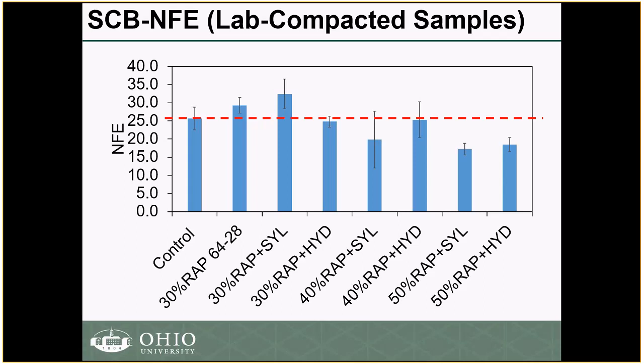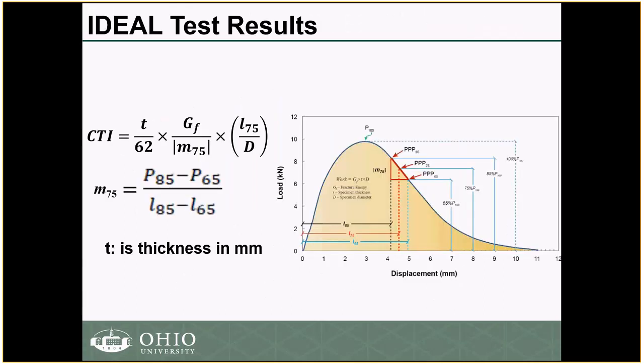But one thing that I want to mention here is that the difference between the values between the lab and the field, lab compacted and cores, were not as significant as with the flexibility index. Another test is the IDEAL. The main parameter from here is what we refer to as the cracking test index.